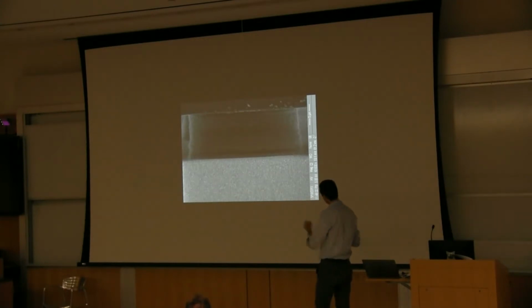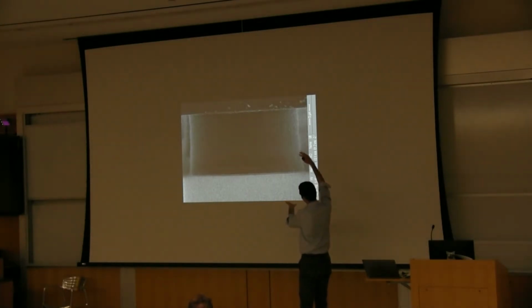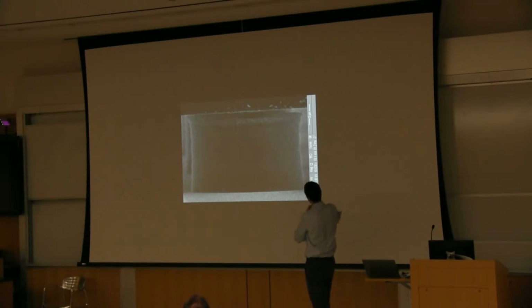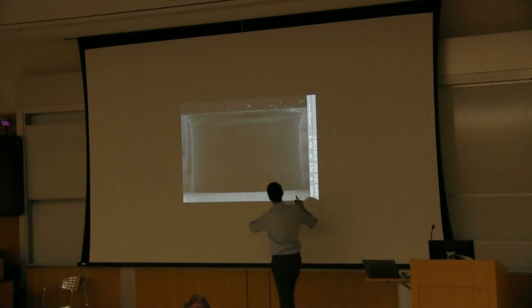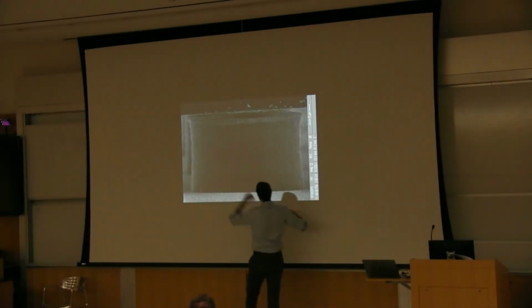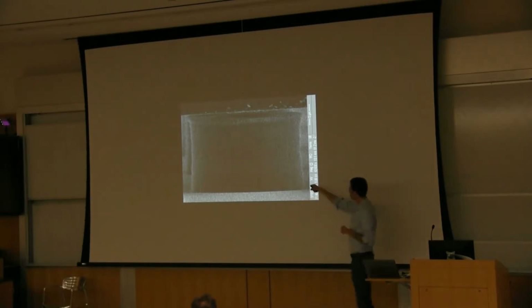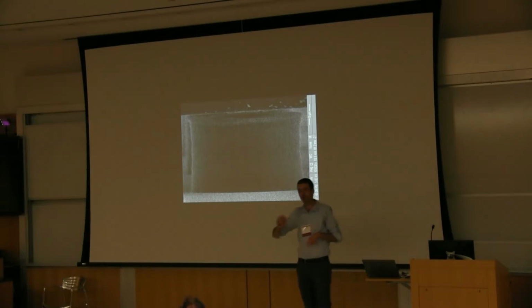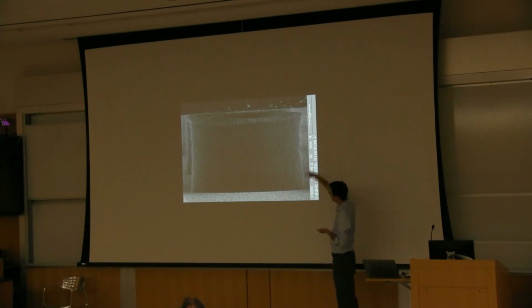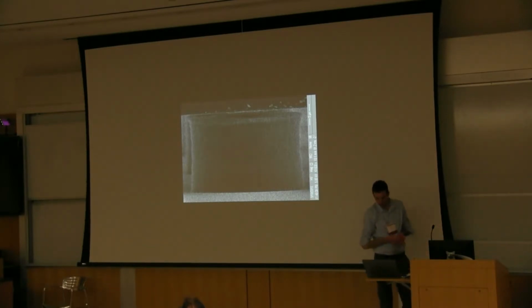at the micro scale. This is a video taken in an SEM, a micro compression test with a flat tip of a carbon nanotube micropillar about 20 microns wide, 20 microns high. And in this case, we've coated the nanotubes with a very thin layer of aluminum oxide, about 1 nanometer, upon 10 nanometer diameter tubes in this microscale forest. And when we did this, we found that the nanotubes, as a collective, rebound from almost full compression, like 90% compressive strain, and they rebound fully. And this let us start thinking about